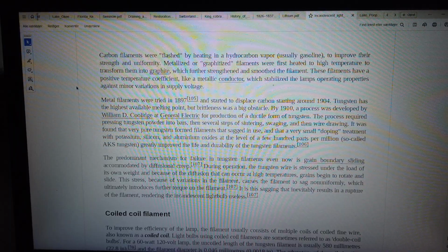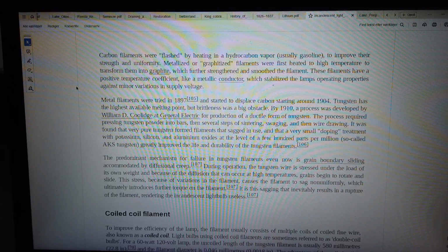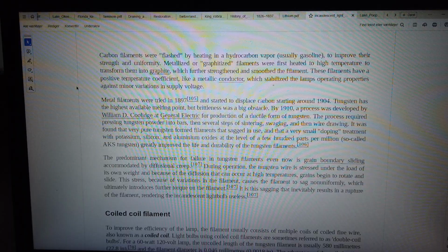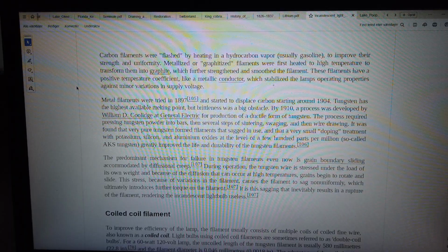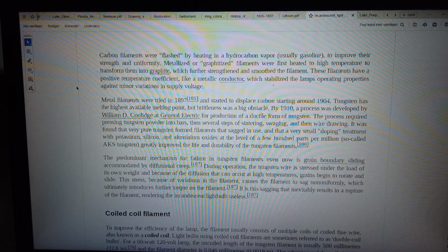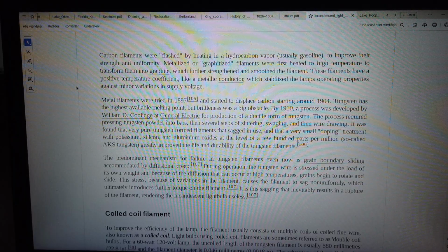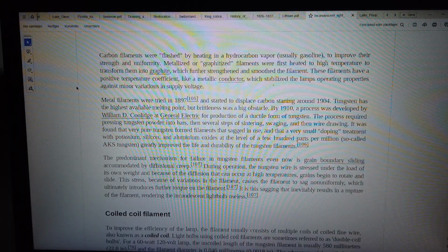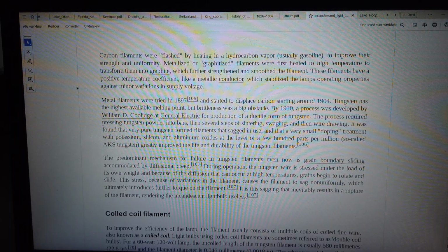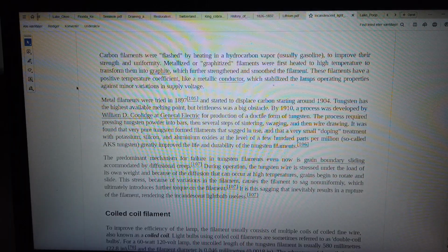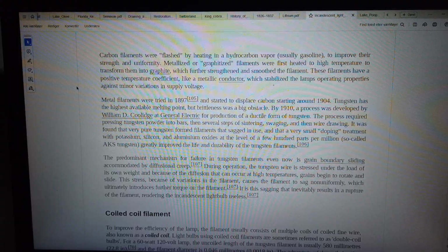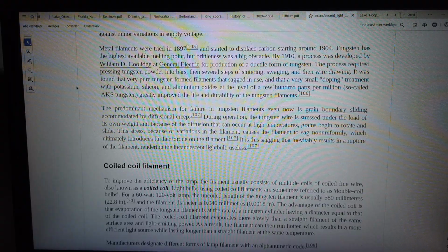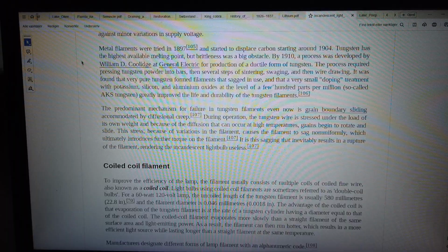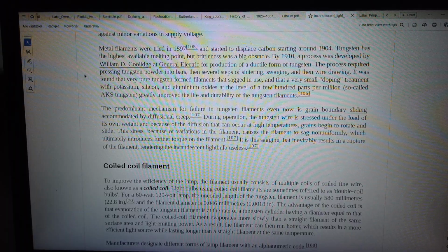Metallized or graphitized filaments were first heated to high temperature to transform them into graphite, which further strengthened and smoothed the filament. These filaments have a positive temperature coefficient, like a metallic conductor, which stabilizes the lamp's operating properties against minor variations in supply voltage. Metal filaments were tried in 1897, and started to displace carbon starting around 1904.